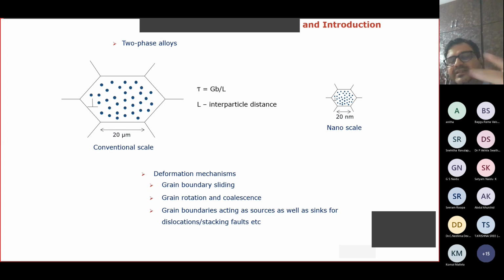material. So here the grain boundary mediated process, in other words, interface mediated process such as grain boundary sliding, grain rotation and coalescence, and grain boundaries acting as sources as well as sinks for either full dislocations, partial dislocations, or stacking faults could be the governing mechanisms.